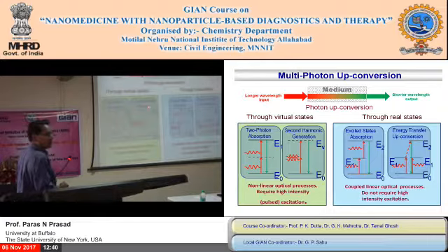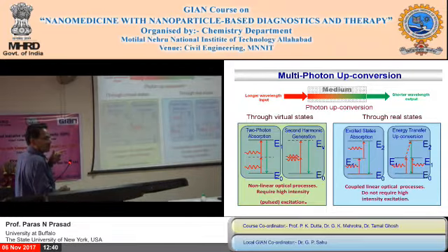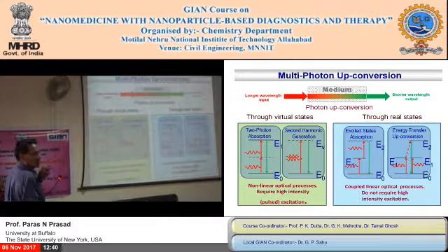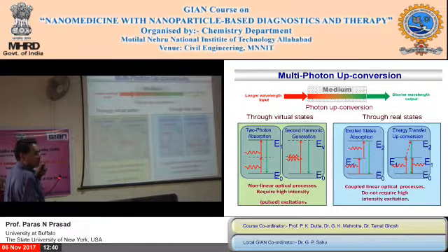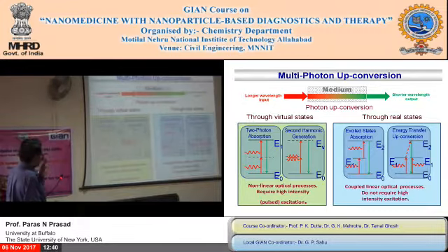The other one is through the second order effect that I told you requires a non-symmetric structure. And you have green pointers. In green pointers, the light that's generated by lasing is 1.06 micron, 1064 nanometers. And then it goes through a material that doubles it to 532, and 532 is green.